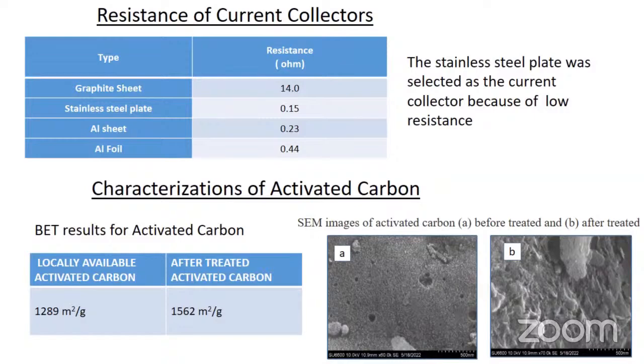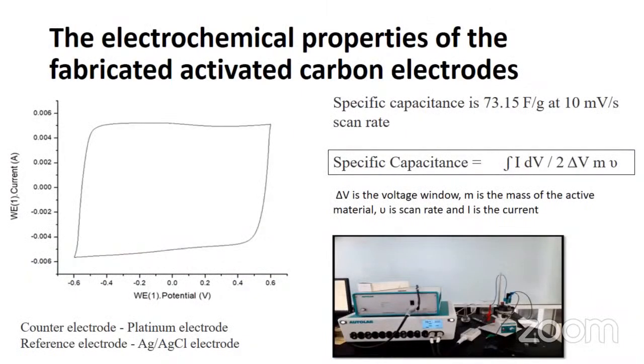When we compare the BET results of the activated carbon, the surface area of non-treated activated carbon is 1289 meters square per gram, and the surface area of the treated activated carbon is 1562 meters square per gram. And you can see SEM images of activated carbon before and after treatment. Here we measure the electrochemical performance. We measure the specific capacitance according to the equation, and the optimum value for the specific capacitance is 73.15 farad per gram when the scan rate is 10 millivolt per second.